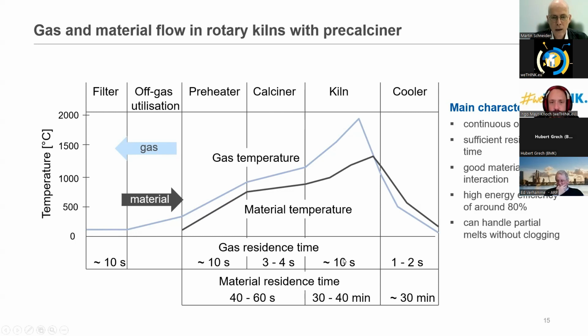You can see here that in the kiln we have a gas residence time, and that is what comes from combustion, which is 10 seconds here in the highest temperature part, but still 3 to 4 seconds in the part that is exceeding 1200 degrees, or 850 to 1200 degrees. And then there is still the cooling phase here. And for the material, it means a very long residence time. Of course, the material takes much longer, and it can even be 30 minutes until the material comes from one end to the other. And that is why we have a complete combustion here.